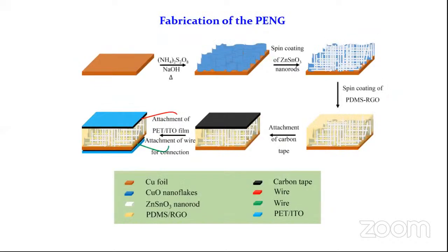So this is the fabrication of the PENG. We took a copper foil and immersed it in ammonium persulfate solution in a basic medium. After heating it, it forms a copper oxide layer. After formation of the copper oxide layer, we spin coated the zinc stannate nanorods on the copper oxide flakes. Then after solvent evaporation, we spin coated a layer of PDMS RGO. After spin coating, we attached the carbon tape as an electrode. After attaching the electrode, we attached two copper wires, as I have said before.